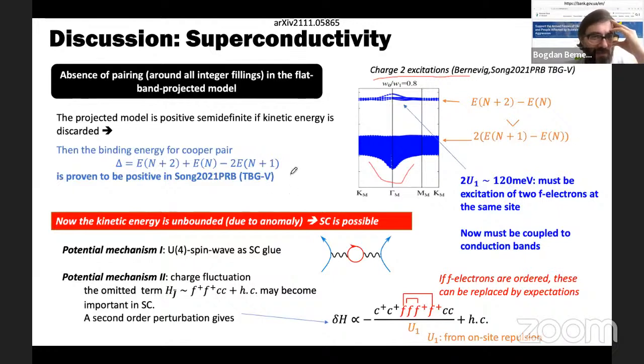we just cannot get superconductivity with phonons. In fact, we can show that if phonon superconductivity existed, it would have to be nematic, it would have to be gapless, but it just doesn't exist because the Coulomb is too large. Now, the one redeeming possibility is off-site superconductivity in the f-electrons, because the f-electrons' interaction is on-site. They're very localized, but off-site, the interaction falls off dramatically. So we're exploring that possibility, but we don't have much more to say, unfortunately. Thank you very much.